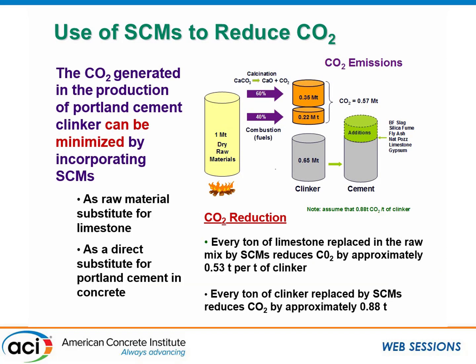So as we look at the raw material substitutions, we can see that if we have 1 metric ton of dry raw materials, we still have the calcination that's going to occur in the decarbonation. In that, we're still going to see the production of CO2. But we can really lower that when we start looking at using blends in lieu of straight Portland cement. And certainly we can see those reductions when we start changing how we blend, using either slag, silica fume, fly ash, or other natural pozzolans. So for every ton of limestone, limestone also can be replaced in the raw mix by SCMs. We can really see almost a reduction in the CO2 content.